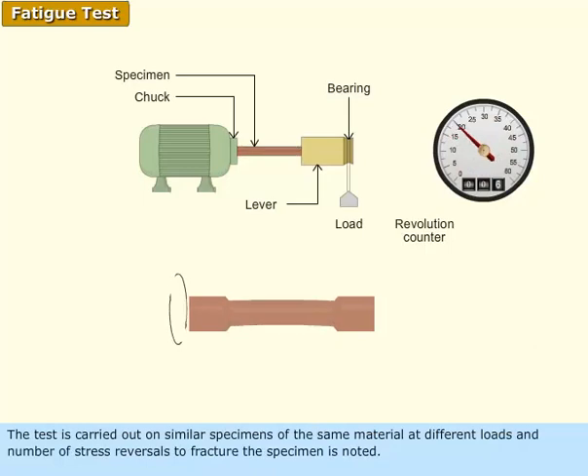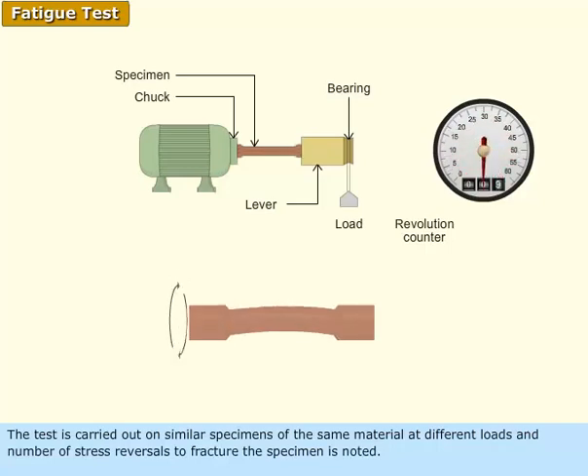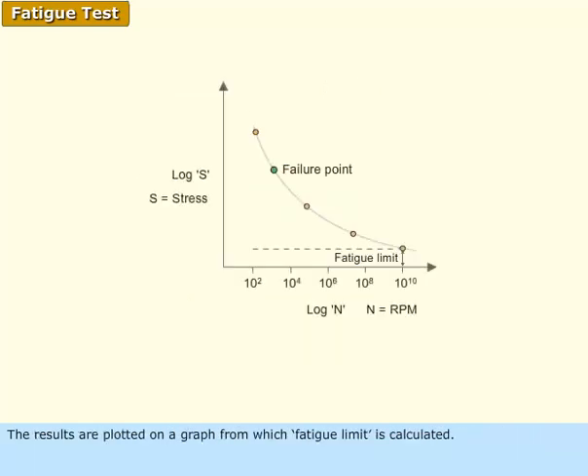The test is carried out on similar specimens of the same material at different loads, and the number of stress reversals to fracture the specimen is noted. The results are plotted on a graph from which the fatigue limit is calculated. A logarithmic scale is adopted to condense the graph.